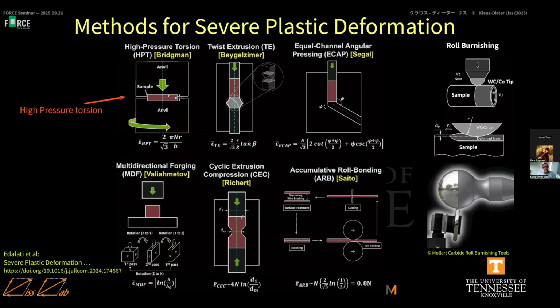Okay, there are many methods for severe plastic deformation. One is high pressure torsion, but we also have twist extrusion, equal channel angular pressing, ECAP. This is also well known or commonly used because it is relatively easy to do. And then we have multi-directional forging, cyclic extrusion compression, accumulative roll bonding, ARB. This is also a very nice technique. And there are lots of these techniques described in this paper, where I also have the figures from. I'm one of the co-authors of over 200 authors in this overview article. The DOI is given here.